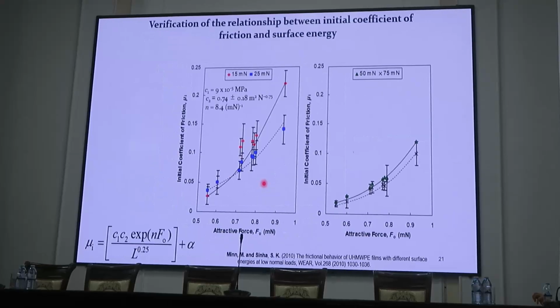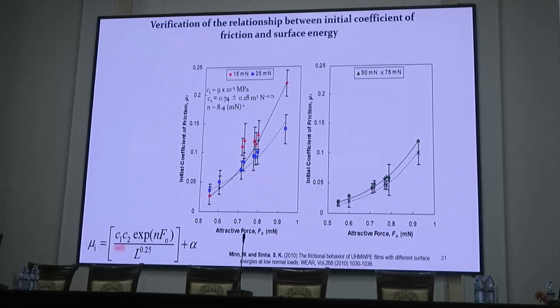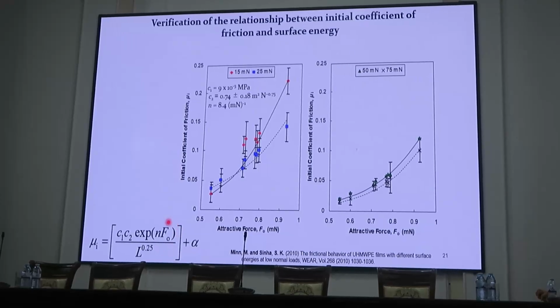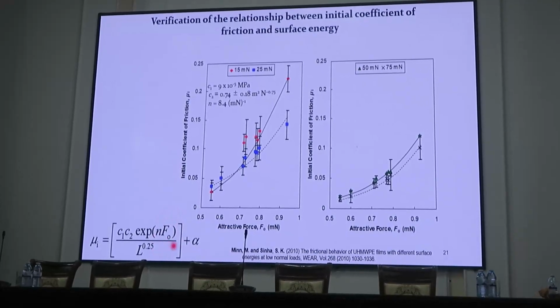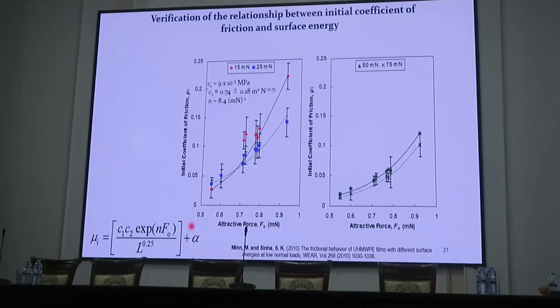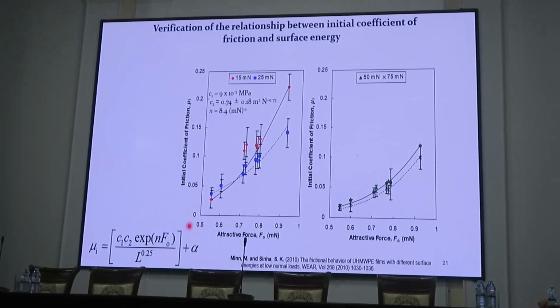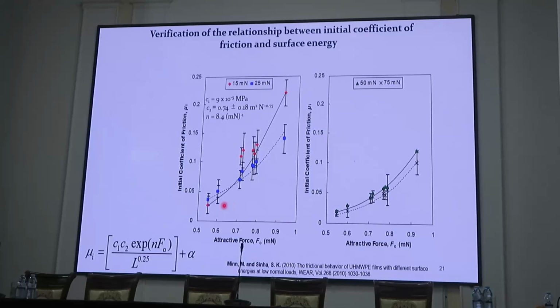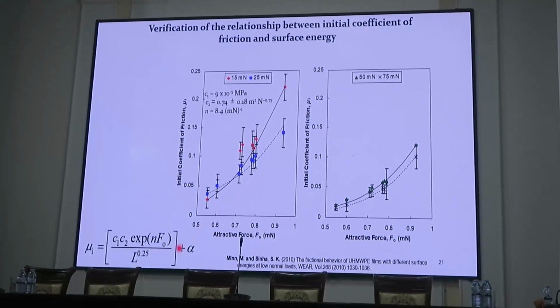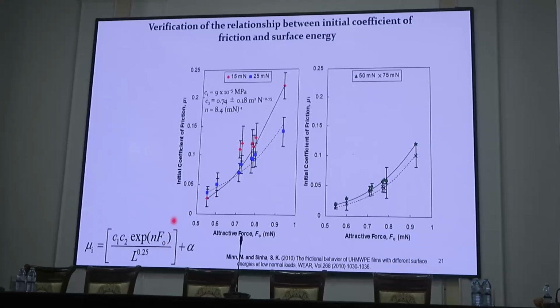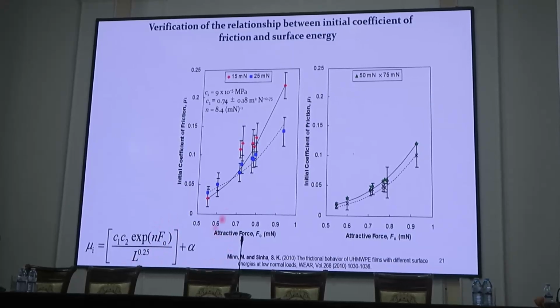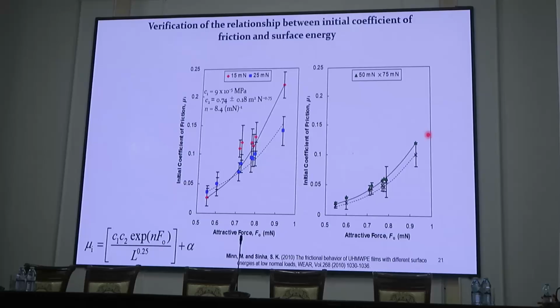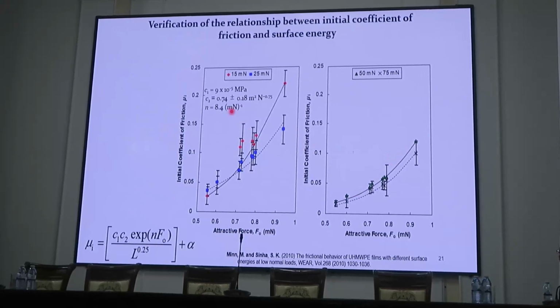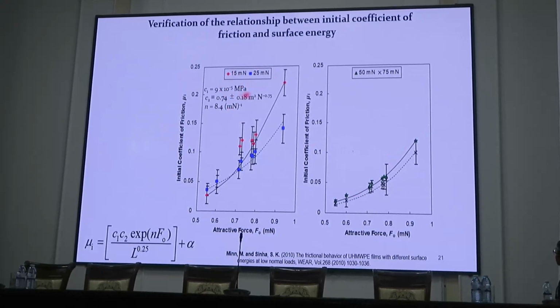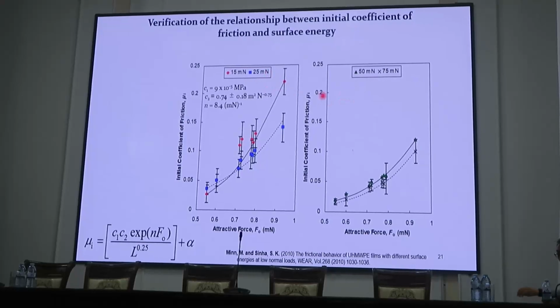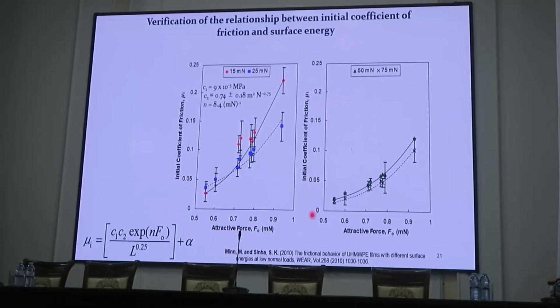And further we found that the coefficient of friction can be related to the attractive force. Using the experimentally calculated attractive force, we have related mu to the attractive force with some constants, and you can see that they fit very well. These were done for high surface energy as well as low surface energy cases.